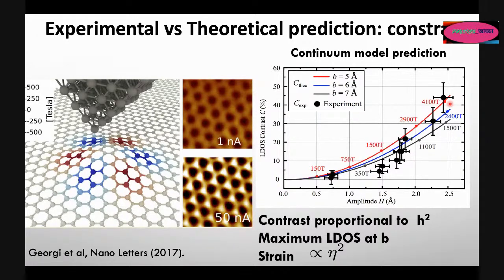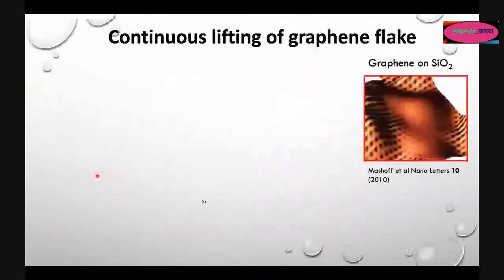Besides, we learned that the contrast depended on the height of the deformation, and the maximum contrast occurred at the distance from the center of the Gaussian at half height of the maximum. That's where the maximum change in the density of states, the maximum charge accumulation, occurs. So basically what I am saying is that these deformed regions trap charges pretty much like a quantum dot, accumulate charges, and these charges are distributed in a very, very peculiar fashion.